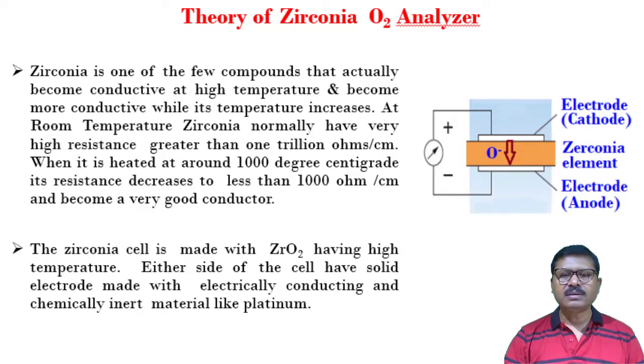The zirconia cell is made with zirconium oxide. So this is the zirconia element, zirconium oxide, and it is normally kept at high temperature to increase its conductivity. Either side of the cell has a solid electrode. This white color is one electrode, this is another electrode. The electrode is made with an electrically conducting and chemically inert material like platinum, and normally the platinum is perforated. So this is one electrode, this is another electrode, and in between is the zirconia cell, the zirconia material.